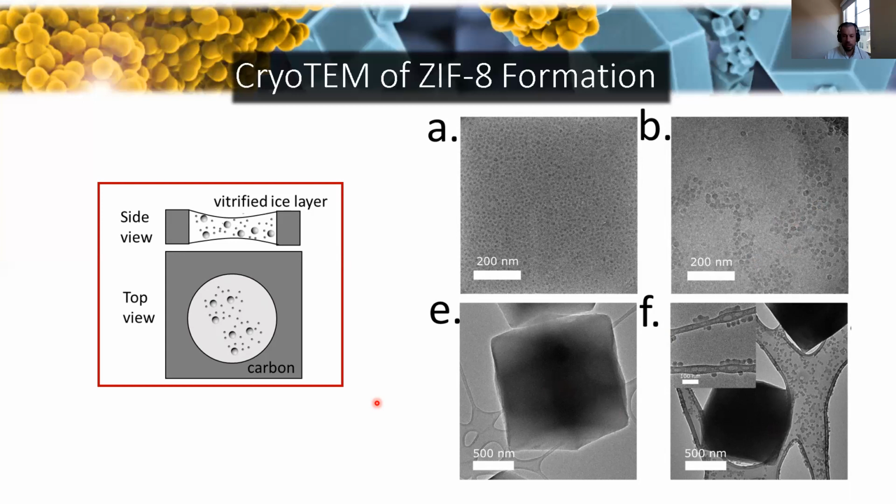or indicated by other analysis, is that the growth of these crystals is very rapid compared to the nucleation of them. And at really any time point that we sample this, we can find evidence of different stages in the formation. And what I'm really tracking here, or what Alana was really tracking here that we're showing you in the cryo images, is really just the bulk average changes that we see. But that's not the full story because, like I said, it's slow nucleation, fast growth. So that's really important to remember.